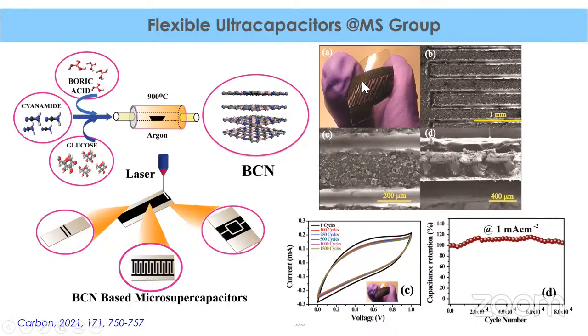So as I said here, an electrode slurry has been coated on an ITO PET substrate, and then it was etched using a CO2 laser. So different designs like this we have also evaluated. For these designs, there is a program, and you can make the designs in the program and give it to the system, and then the laser selectively etches out the electrode as per your design. And then you can put the solid gel electrolyte on top of this substrate.